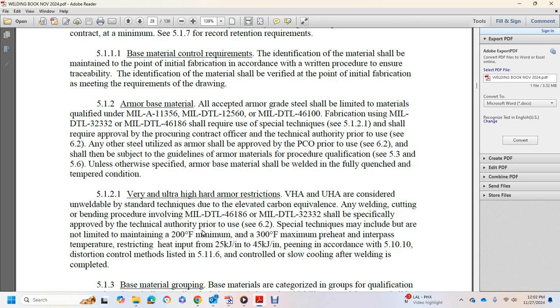Special techniques include, but are not limited to, maintaining a 200 degree Fahrenheit minimum and 300 degree Fahrenheit maximum preheat and interpass temperature, restricting heat input to 25 kilojoules per inch minimum and 45 kilojoules per inch maximum, peening in accordance with 5-10-10, distortion control methods listed in 5.11.6, and controlled slow cooling after the welding is completed.